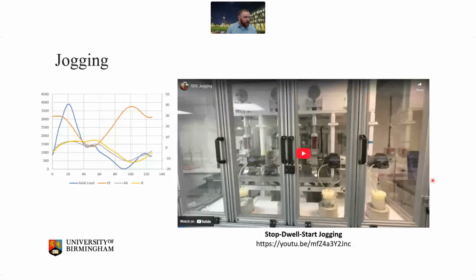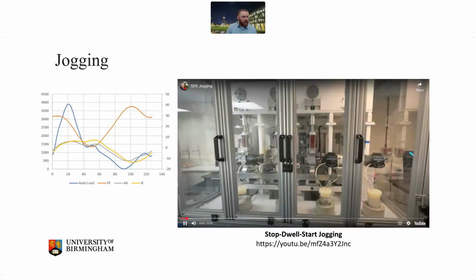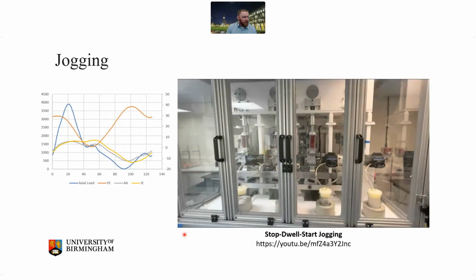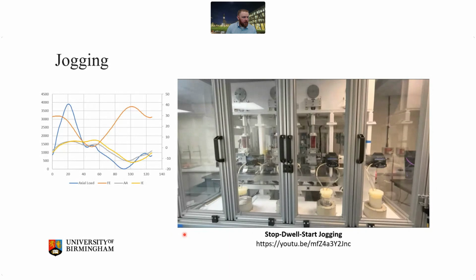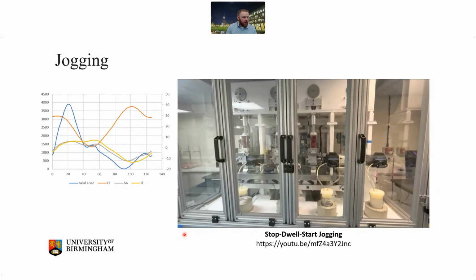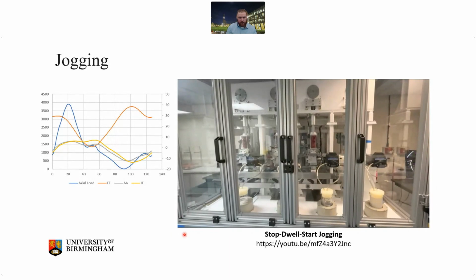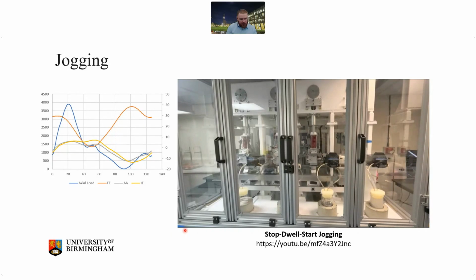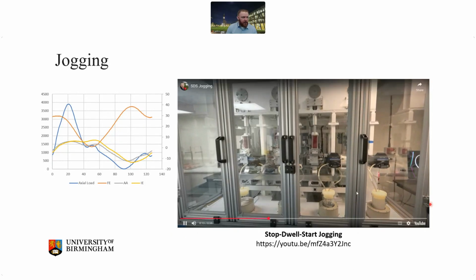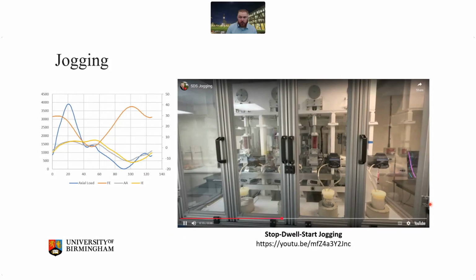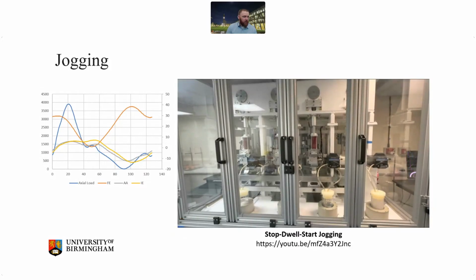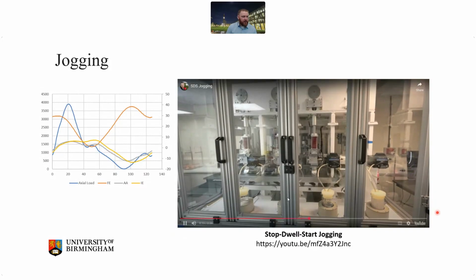So it's a lower N on the cohort, but essentially we can run these simulators through much more severe contact. So we'll touch a little bit on some of the adverse loading profiles that are typically seen in the literature, but we can introduce stop to start. And one of the nice things that this highlights is that, with the capability of these simulators, what we can start to do is iterate through profiles.